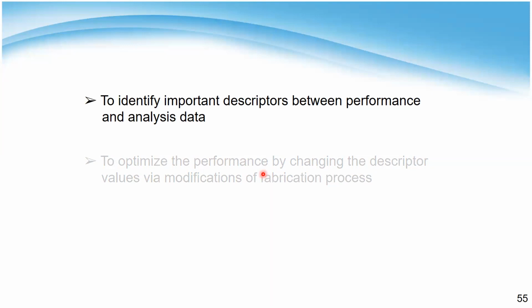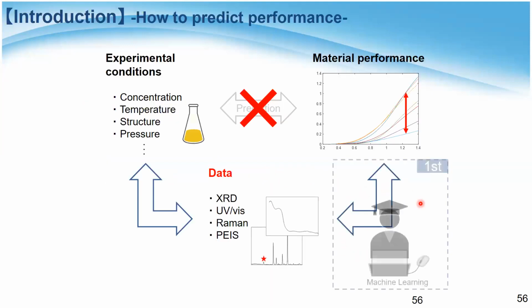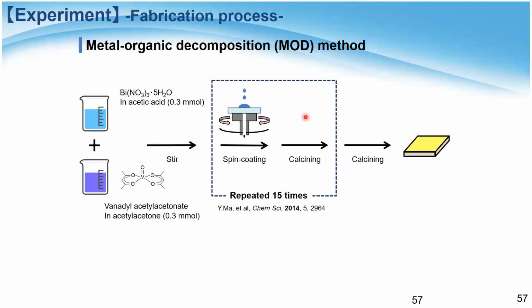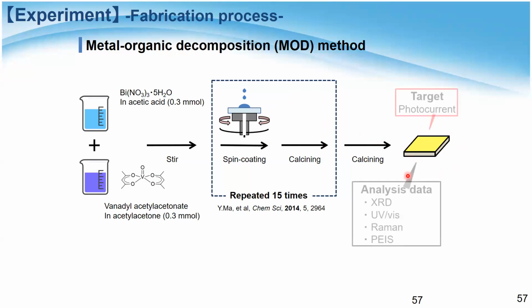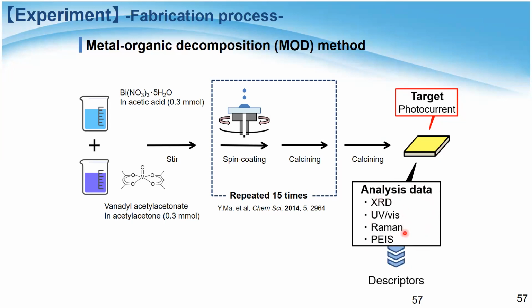This sample is prepared by the metal organic decomposition, namely the MOD method, in which the bismuth precursor and vanadium precursor are mixed and then spin coated and then calcinated, and these processes are repeated to generate the thin film. And then we did the analysis of each material by various analytical methods, and target values such as photocurrent, and they are used as descriptors.